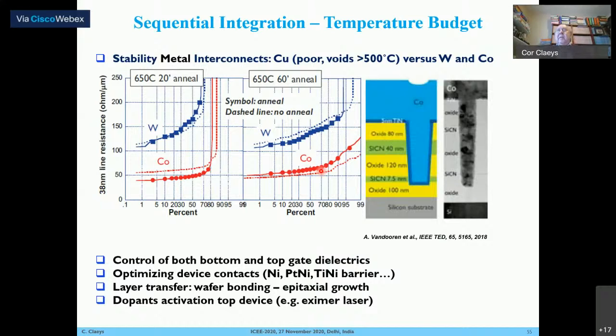That means in the top layer, you can, for instance, implant your dopants. But if you do an implantation with the dopant, you need a temperature treatment for two reasons. One, to activate the dopants. Secondly, to anneal out the implantation defects. If you do that in silicon, you need high temperatures, or you have to work with special techniques like, for instance, excimer laser annealing.